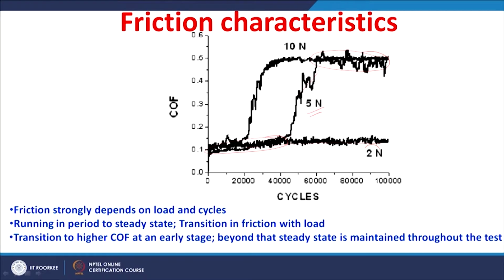So, there is a transition with the fretting duration for the test done at 5 Newton load, and if you look at the test done at the 10 Newton load, you have the transition occurring even at an early stage. The coefficient of friction was low in the initial stages, around 20,000 cycles. Immediately after 20,000 it went up to 0.5 average coefficient of friction in the steady state, and this is reached around 40,000 cycles.